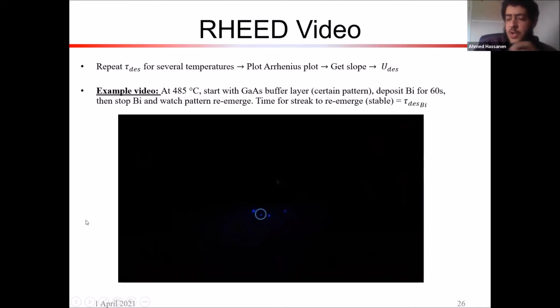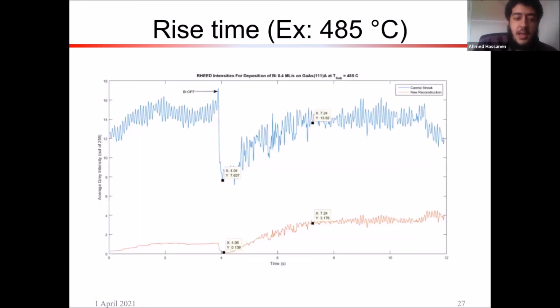So because the bismuth has been shut off, what we really want to see is how long it takes for the streak to reemerge. But this is a translation of how long the bismuth took to desorb. And so this is what we did. We plotted, basically using some image processing, just the change in intensity of this dot or streak, if you will.